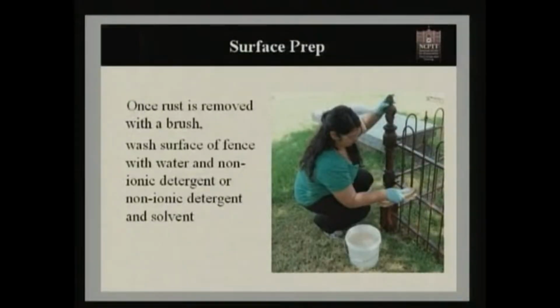Once the rust is removed with our wire brush, we then want to wash the surface of the fence. Now I know this sounds kind of odd to wash metalwork, but keep in mind these are exterior fences, they get wet all the time. But we want to use a non-ionic detergent, or a non-ionic detergent that can be mixed with a solvent. And in doing this, what we're doing is we're removing that biological growth.